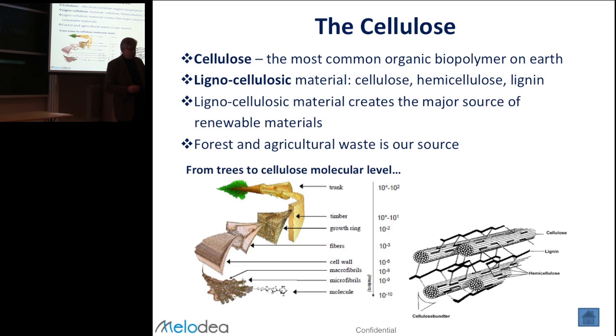A lot is transported to Europe, mainly to Belgium, where they make a resin that is used by the industry that is making cast iron, the foundry industry. They use this to glue the sand. When you make cast iron, you have a sand mold which has the flowing iron in it. But we take that kind of material that is a derivative and make an alcohol of it, which we call furfuryl alcohol, that polymerizes at 138, right? Start to remember that.